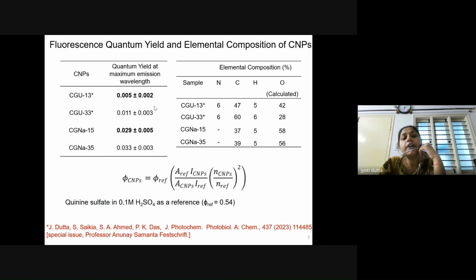However, for the second set of nanoparticles, which were synthesized using glucose and sodium hydroxide, the composition was more or less the same. You can see the hydrogen elemental composition, the oxygen content, as well as the carbon content were in an appreciably similar range.